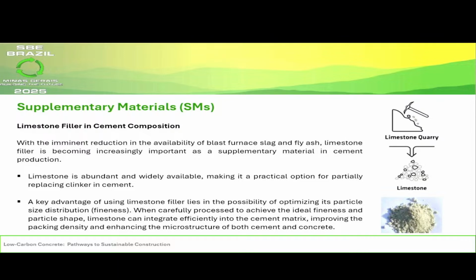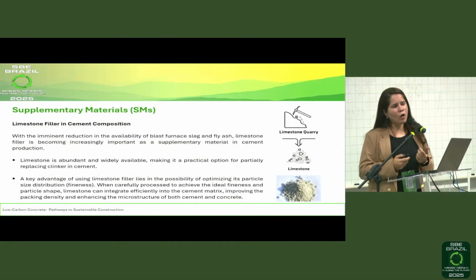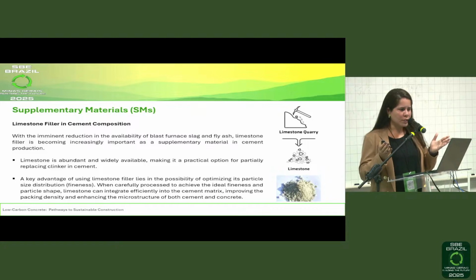We also have limestone filler. Everyone that has a cement factory has a limestone quarry, and if you work on the grains, we can have a much better result. Nowadays, there are many studies in the world that work on the granulometry of separated materials in order for us to get the thinnest material, because they are different. If you put everything in the mill as it's done in Brazil, we don't extract the best grain. When I talk about clinker and limestone, if we do separate grinding, there are many relevant studies on the theme, and it's very important so we can develop cement with more limestone filler without losing performance.